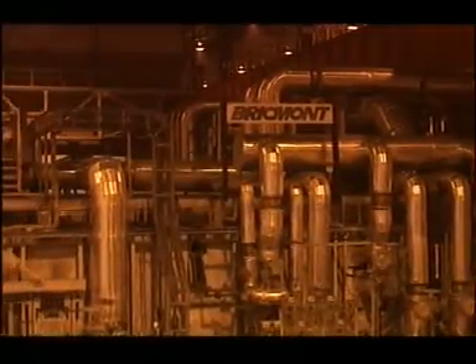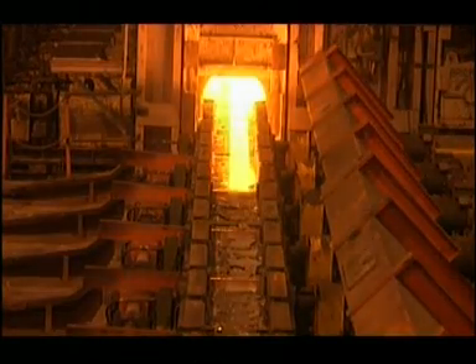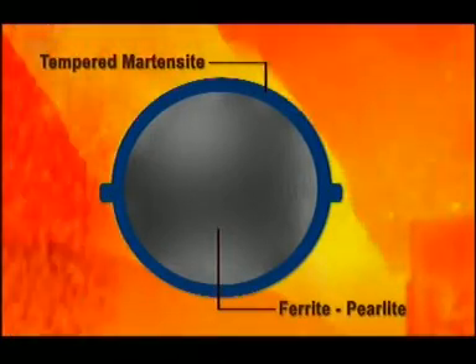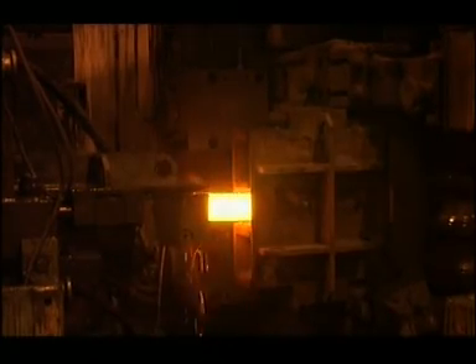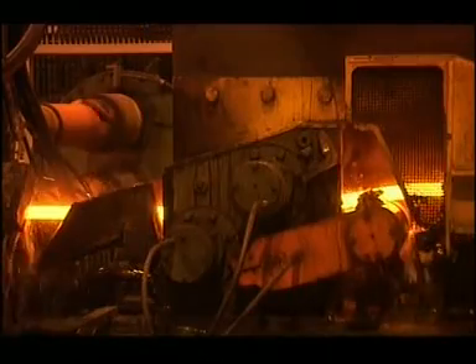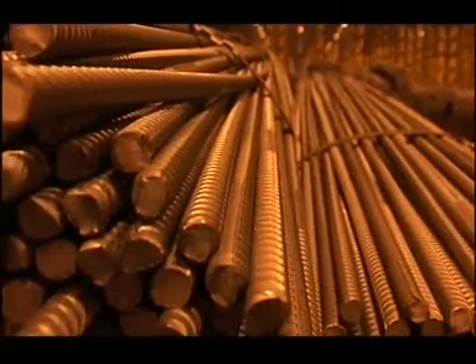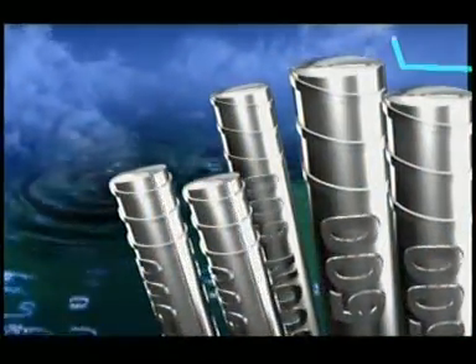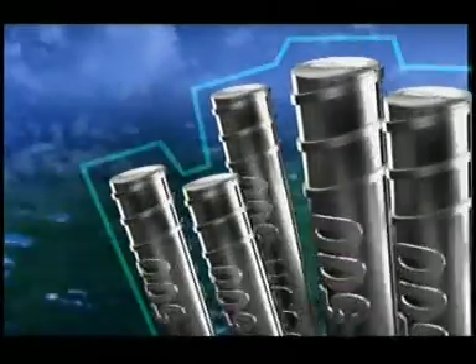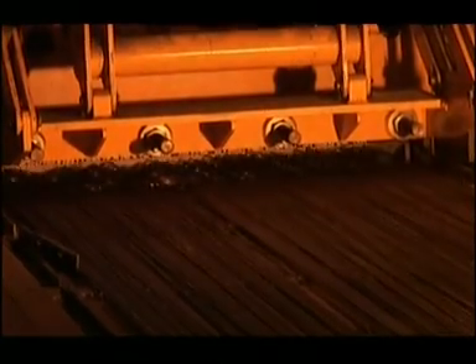The precise control of the thermomechanical treatment process results in a uniform and thick tempered martensitic rim, completely free from internal stresses. This martensitic rim improves the corrosion resistance of Tiscon 500 as well as the fatigue strength when compared to traditional cold twisted bars. Corrosion resistance gets further improved owing to less surface area. Advanced technologies like the loopers and sensors ensure bars within close weight tolerance. This further reduces consumption of Tiscon 500 because of extra length per unit mass.